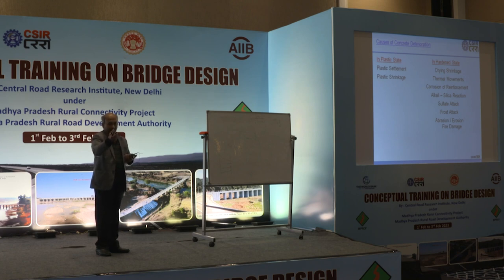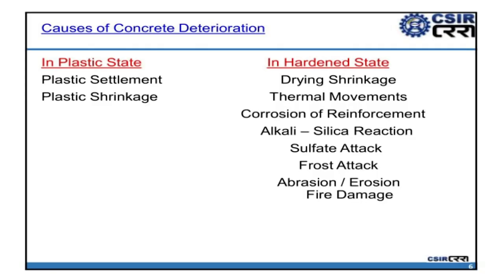From the moment concrete is placed, durability problems will start if you are not vigilant. In the plastic state, two types of problems come up: plastic settlement and plastic shrinkage. Aggregate is heavier so it sinks to the bottom; water comes to the top and accumulates behind aggregate, and after drying, a void is left — called a settlement void — with a settlement crack on top. The other problem is shrinkage cracks when bleeding water evaporates due to high heat or wind.